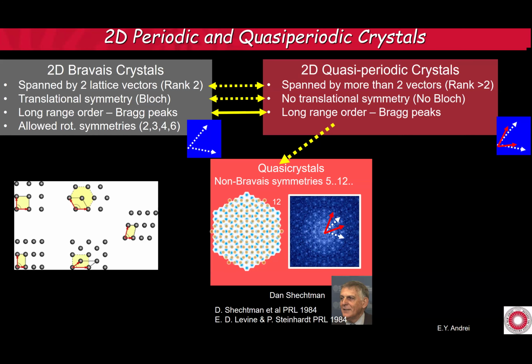Yes, right. And the decagonal phase is particularly interesting because it's aperiodic in the basal plane, periodic perpendicular. So you get metallic transport along the periodic direction, and again, just horrible flat resistance. So a beautiful experimental difference between these would be the metallic behavior you see in the 2D Bravais and just temperature independent. Interesting. So that would be a fascinating comparison between bulk quasicrystals and these. Okay, all right, homework.